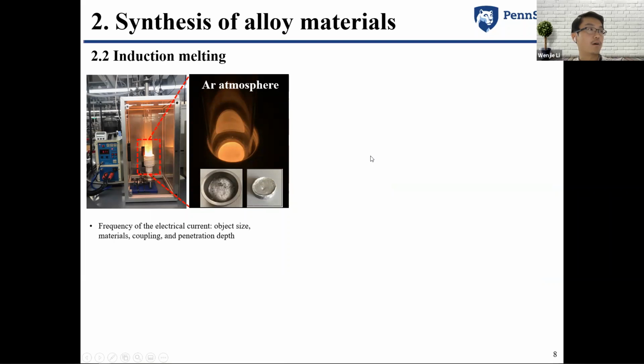Another commonly used synthesis method for alloy materials is induction heating, which is a process of heating an electrically conductive object through heating inside the material by magnetic induction. This is a setup that we have inside the building, with a heating coil surrounding the quartz tube. We put the materials in different crucibles inside, and by gradually increasing the current,